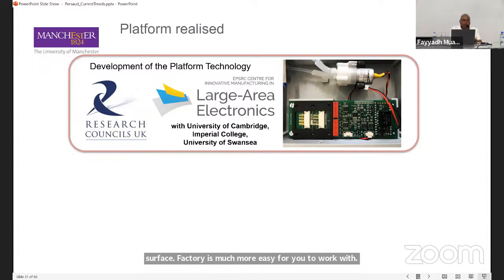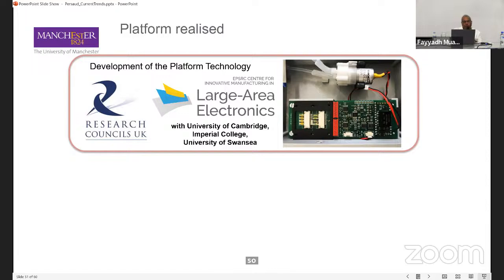So graphene, you can immobilize it between a source and drain electrode. So if you take the ink containing graphene oxide, you can spin coat it, you can inkjet print it between two conducting electrodes. Just the graphene oxide, yeah, without any mixture, because you don't have to, and you end up with something that is conducting. It behaves like a transistor, which turns on at a very low threshold.